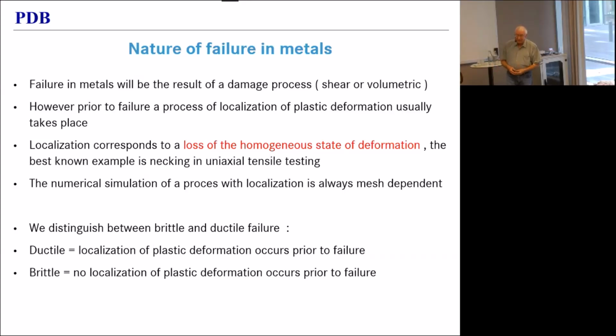Now, the important thing that we're going to try to convey today is that brittle and ductile are not material properties. Any material is brittle and ductile depending on the state of stress to which it is subjected, and it will have to be treated accordingly.